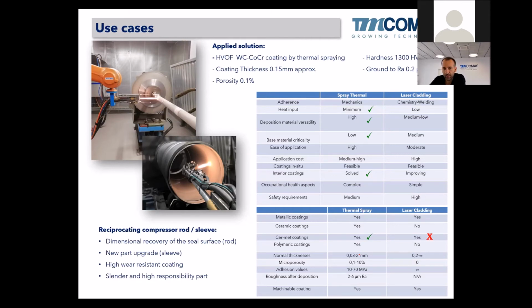Coating thickness must be kept low because it's a very tough, hard and brittle coating, so we cannot go for a very high thickness in this case. So why have we chosen HVOF instead of laser cladding? Well, in this case it's clear, no? We have an inner coating and we don't have an inner cladding head. So the only way to clad this is by thermal spray.